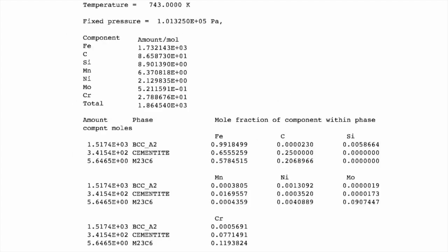And I gave you an example previously, but this is the case at 743 K for the iron, carbon, silicon, manganese, nickel, moly, chrome system, and at ambient pressure. And we've got three phases stable at this particular temperature. So we know which phases are stable. We know the quantities of each of these phases, because this is the amount of each phase in the number of moles. And we know the chemical composition of each phase here.